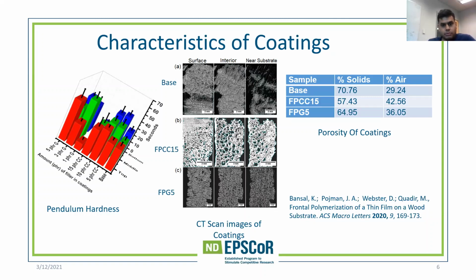In conclusion, I would like to say that we were able to formulate thin films using frontal polymerization on wood substrate. Their front velocity and front temperature can be controlled, and their porosity can also be controlled. And we did get an 80% conversion of monomers. These coatings are 100% solids, and they are on-demand curable coatings.